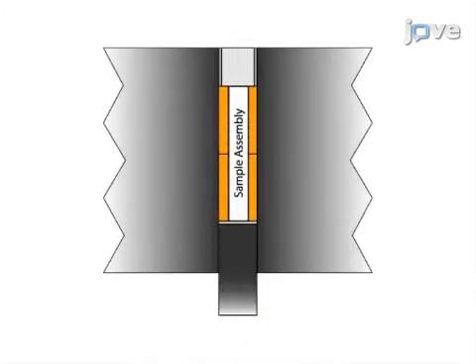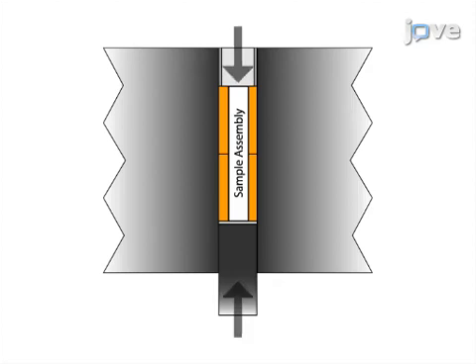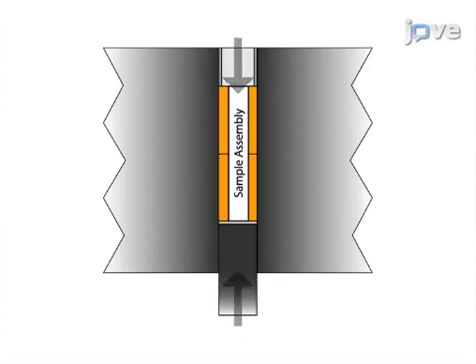The final step is to pressure the sample and then heat to the desired temperature. After enough time has passed to achieve equilibrium, the sample is quenched by cutting power to the resistance heater.